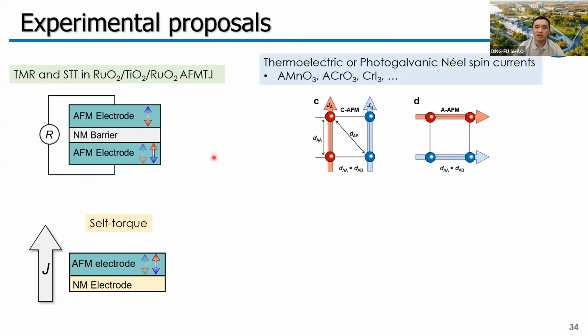And from the structure, we found many antiferromagnets have a small distance, such as the manganese or chromium-based perovskites or the widely investigated chromium iodide. Most of these materials may be insulating, so it may be difficult to use the electric field to generate the Néel spin currents. On the other hand, we can use a temperature gradient or laser to generate thermoelectric or photo-galvanic Néel spin currents, which may introduce interesting functionalities.